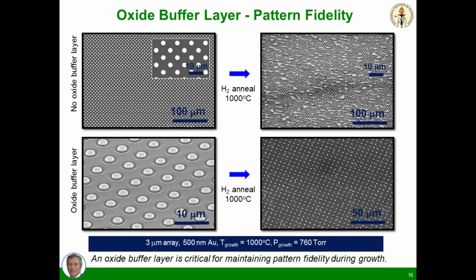So we have to grow these microrods. We do this by the so-called vapor-liquid-solid growth method. We take little balls of metal catalysts, and then we expose them to a silicon precursor in what is a toaster oven. It's a little more sophisticated than that. It's 1,000 degrees centigrade with mass flow controllers, but for all purposes at atmospheric pressure, it's just a tube furnace oven that contains our silicon precursor. And wherever the silicon dissolves in these metal balls, it will then continue to dissolve until it supersaturates and then